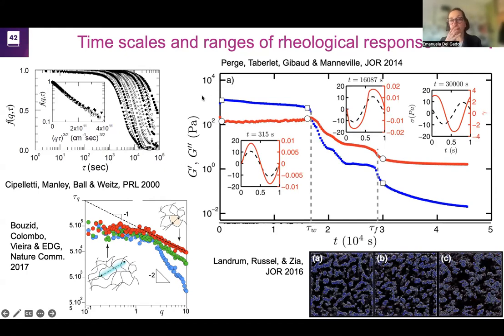And so you can see that over time, basically as they are cycling through the stress, the gel actually fluidizes, right? G prime becomes smaller than G double prime, but it does so in steps, quite abrupt steps, telling us again that there is in fact a multi-level structure that is pulled into the fluidization of the system as time goes by and as the stress is applied cyclically.